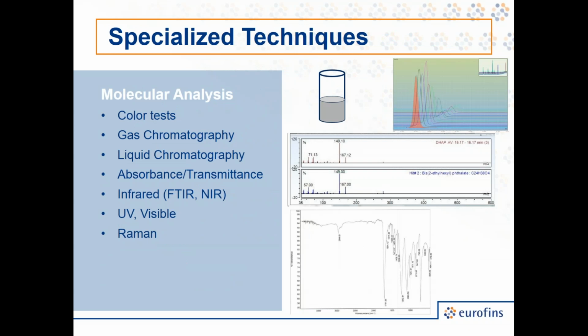So then we get into our specialized techniques, your gas chromatography. Of course, we can match that with flame ionization detection, thermal conductivity detection, which is good for gases, and mass spectral detection, where we can detect over 300,000 different volatile and semi-volatile components. Obviously, liquid chromatography for things that are not volatile. And basically, the rule of thumb there is if it boils at 175 degrees centigrade or less, we're going to use GC. Higher than that, liquid chromatography. But there are some exceptions, and we can do things with derivatization to kind of move from one side to the other. UV absorbance and transmittance is very powerful.